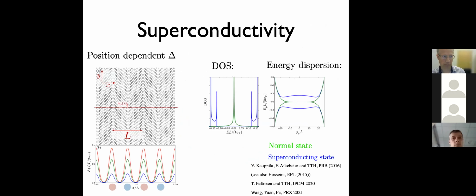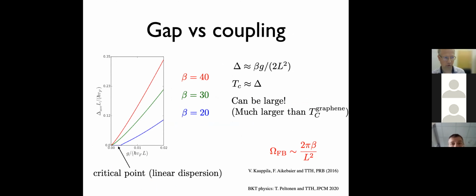We have studied what happens if you now add attractive interaction here. What you get is a position dependent delta, and you can also look at, for example, the superfluid weight. It is finite, like in the previous case. The BKT temperature is finite, and so you would expect this system to have superconductivity if there is attractive interaction. The scaling of delta versus the coupling strength is also linear here, but actually it has a quantum critical point, which becomes smaller and smaller as you increase beta.